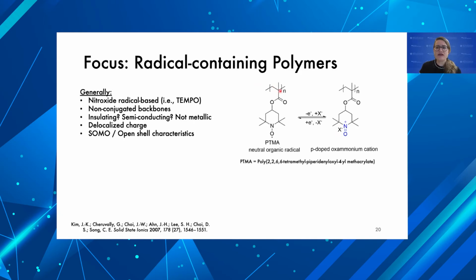One of the interesting features is that this has a non-conjugated backbone, so it's really different from conjugated polymers. So there's been some debate in our area about how electronically conductive these polymers really are. It's agreed that these polymers are not metallic-like, but there have been observations that these are insulating or semiconducting. The charge, this is a typo here, the charge is actually very localized on the nitroxide radical. So because you have this localized charge, it gives you different properties and a different mechanism of energy storage.